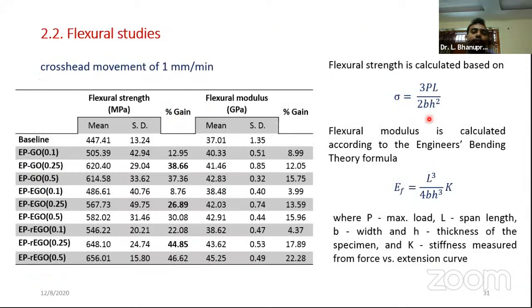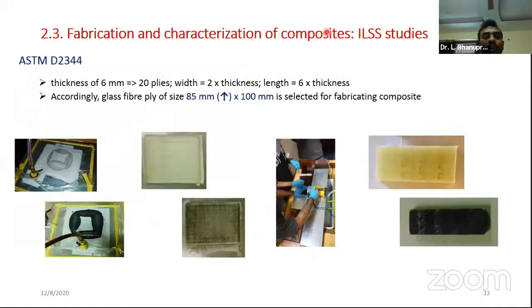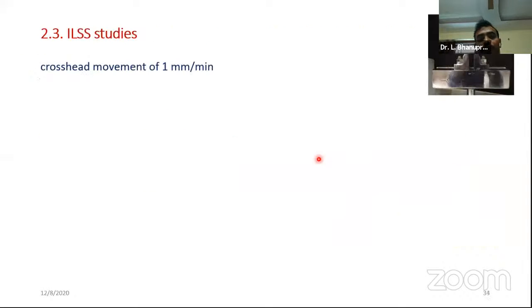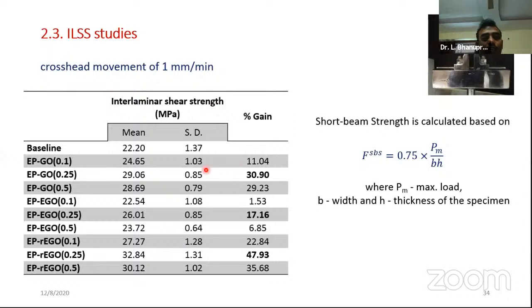And according to the ASTM standards, we have calculated both the flexural strength as well as the modulus, and we could notice very good improvement at the fiber reinforced composite level, up to 44% improvement in the strength, and the modulus was also improved. Similarly, interlaminar shear strength has also been tested, and it is a very critical study, we can say. Interlaminar shear indicates the bonding strength between the fiber and the matrix. So that is also improved with the presence of nanofillers. Nanofillers have promoted the bonding between matrix and reinforcement, where we could notice 48% improvement with RGO at a very, very low concentration, that is at 0.25 weight percentage.